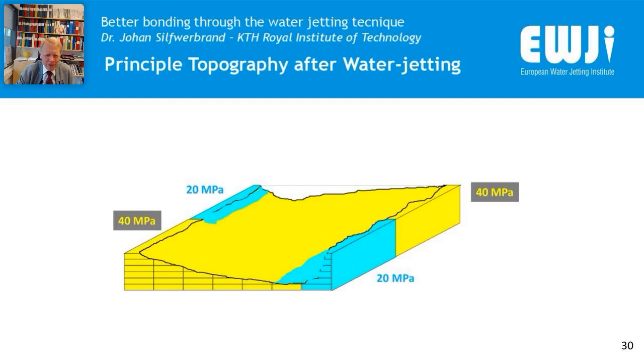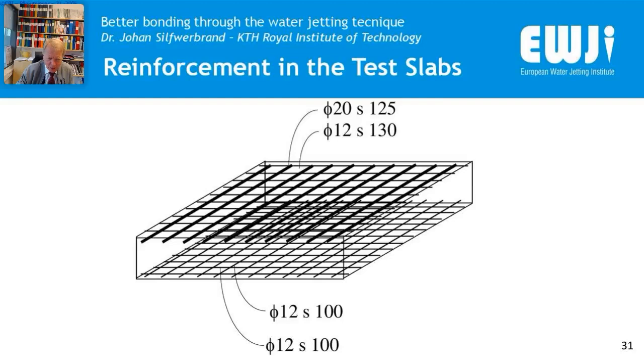Here are other colors. So blue is still 20 megapascal, but the high quality is here 40 megapascal. This is a result where you have left most of the 40 megapascal concrete, and you have removed most of the 20 megapascal concrete. So good result. And in order to make it a little bit more complicated for the equipment, we had also reinforcement meshes, both in the top and the bottom of the specimen.